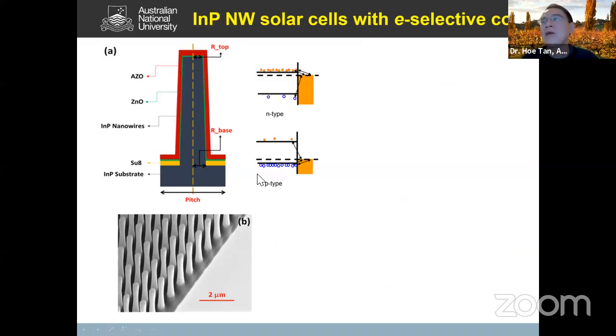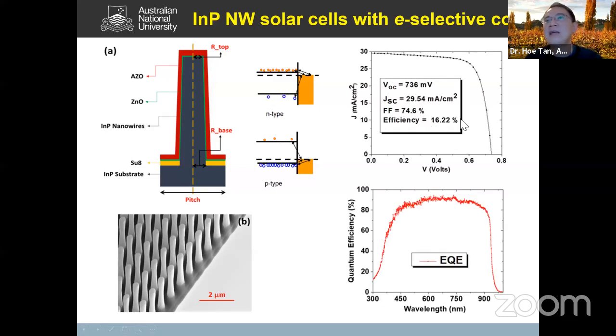So you can see we have improved our growth such that we have nanowires which are fairly uniform in length. And then in our fabrication process, we developed a new fabrication procedure where we conformally coat it with a zinc oxide layer. Zinc oxide acts as an electron selective contact as shown here. And then again, conformally cover it with another contact layer like aluminum zinc oxide. Okay, so by doing all this, improving the fabrication process, you can see we can significantly enhance the efficiency of our nanowire solar cell to in excess of 16%. Okay, and this is the quantum efficiency measurement. It shows you it's fairly efficient, close to about 90%, the external quantum efficiency for a broad spectral range from the indium phosphide nanowire.